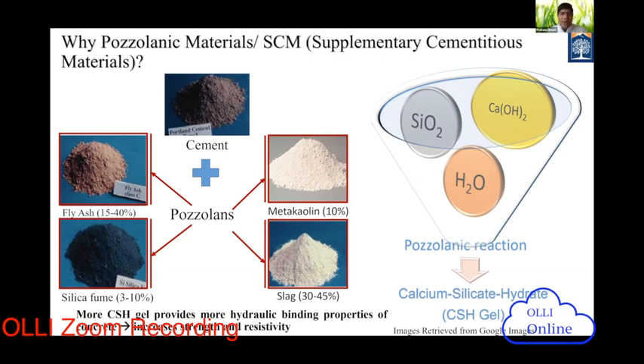That's what we want: a heavy amount of calcium silicate hydrates. It's a gel-type compound. You cannot see it with the naked eye, but you have to go through scanning electron microscopy to see the interior of the cement matrix and how the CSH gel has been formed within it.